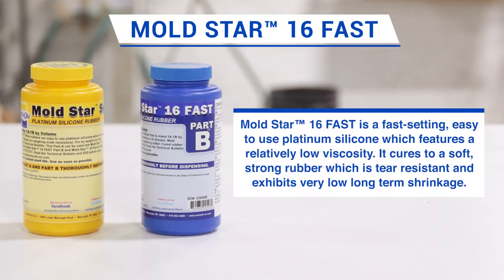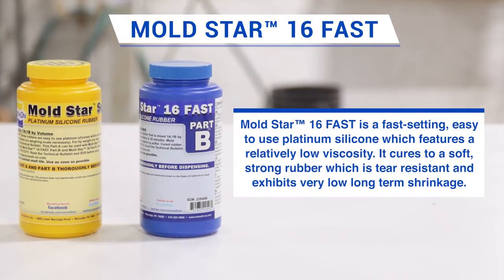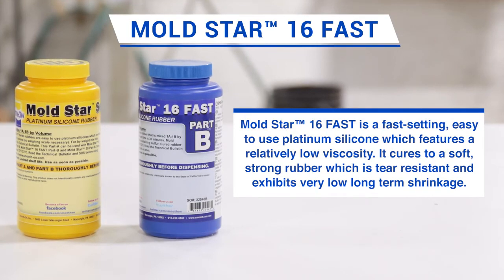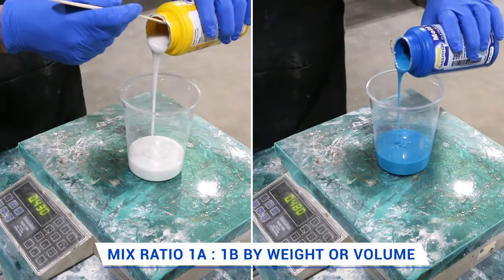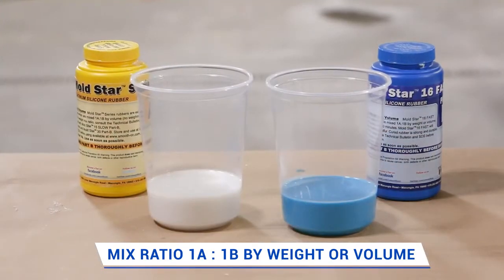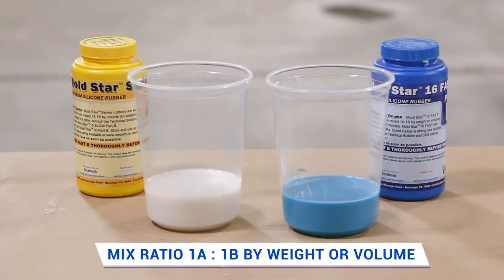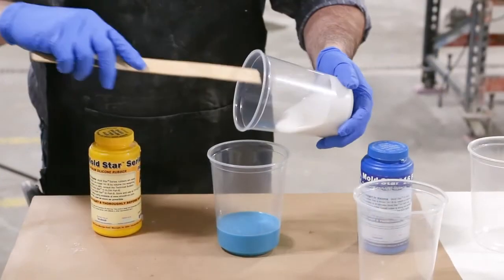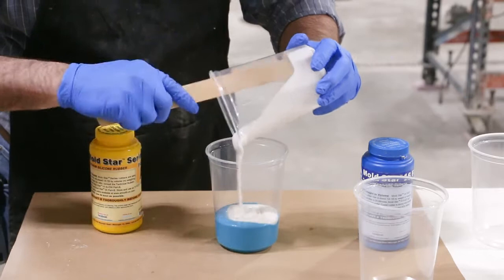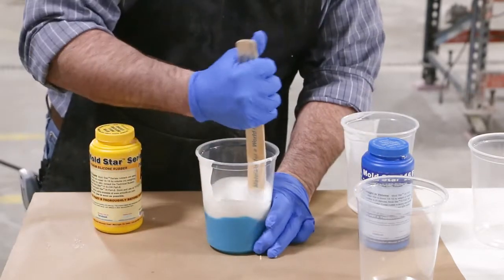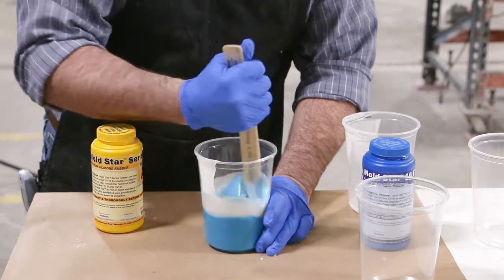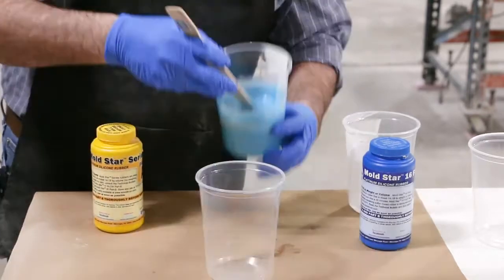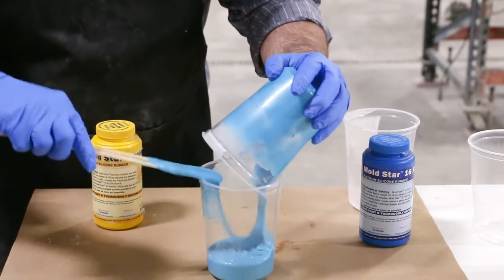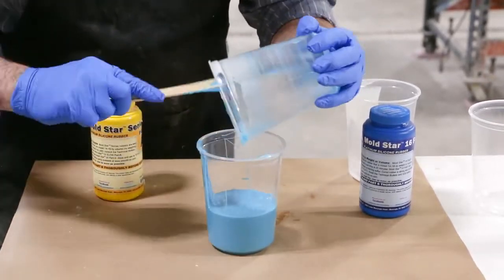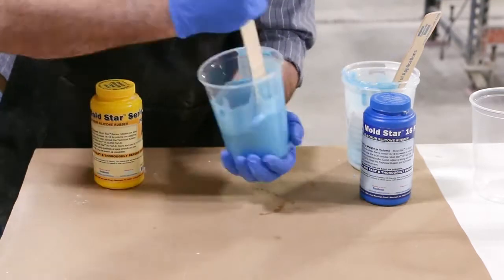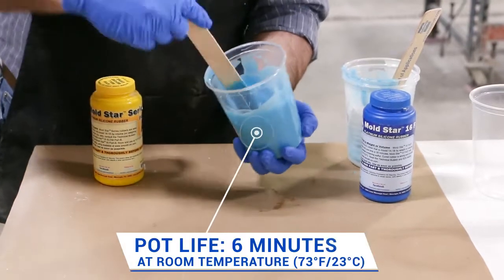I used MoldStar 16 Fast silicone mold rubber for creating this mold. Dispense equal parts A and B by weight or volume into clean mixing containers. Combine the components and mix thoroughly, scraping the bottom and sides of the container. Continue mixing until well incorporated when there are no color striations present. Pour this mixture into a new clean mixing container and continue mixing to ensure a thorough mix has been achieved. Work deliberately and quickly since the pot life is 6 minutes.